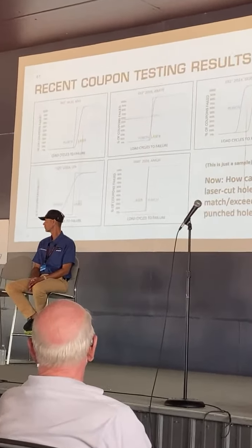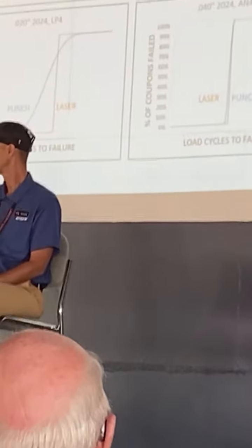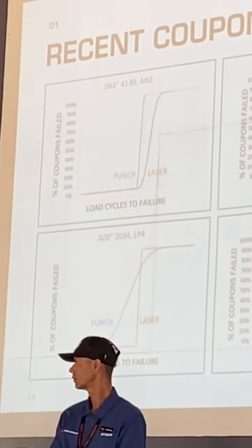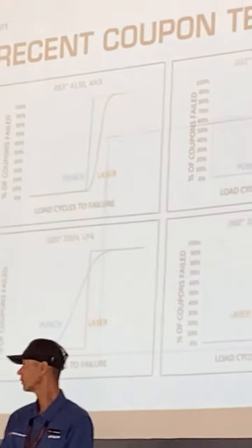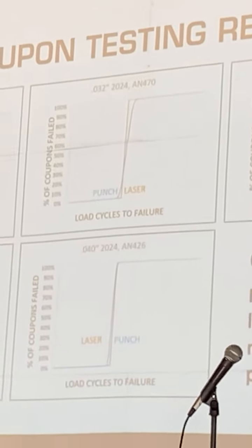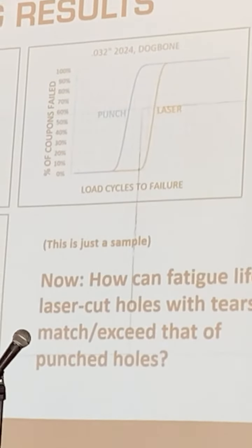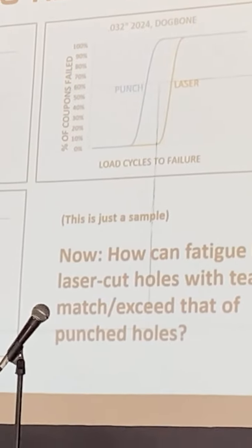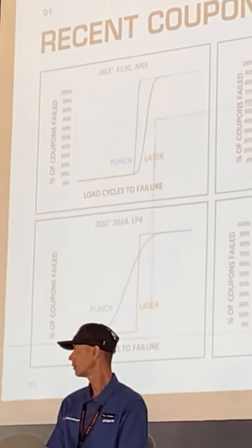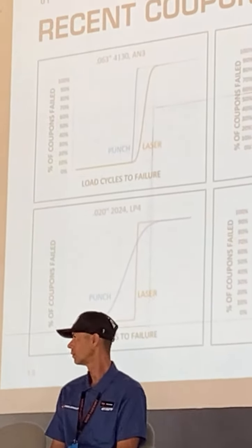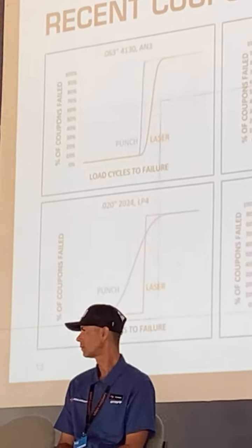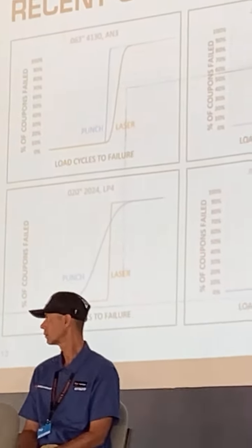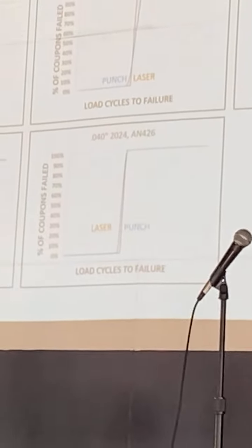And here are our recent coupon testing results. I want to qualify this because we are not through with testing yet. And although things are looking hopeful so far, it doesn't mean we're not going to find an area in which the life is reduced. But what you see here is the probability that a crack would occur or a failure. This is to full fatigue failure, so I should qualify that. We're testing these coupons until they completely break in both the punched configuration and then taking the same configuration and repeating it in a laser cut configuration.